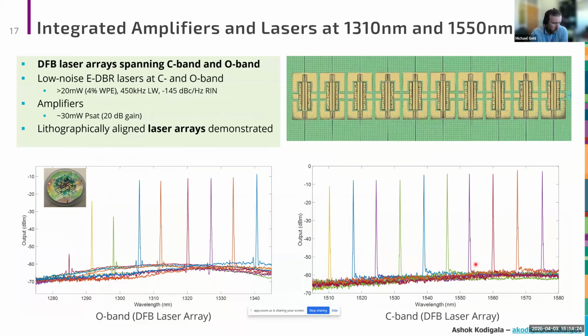So then, building on these low loss waveguides, we've done quite a bit of work to integrate III-V materials for lasers and amplifiers. This is an example of our integration of O-band and C-band gain material on silicon waveguides. You can see on the bottom here an example of how we can span both the O and C band. These are, I guess, two different gain stacks, but then within that gain stack, we can tune the design just by changing the lithography of our silicon waveguide.